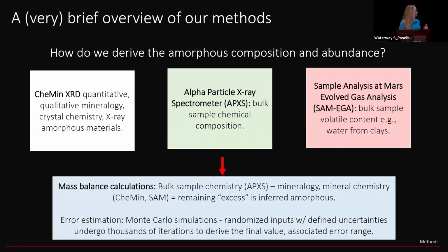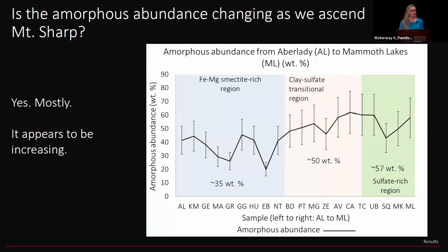And then this gets fed into a mass balance calculation, where we basically subtract the mineralogy and the mineral chemistry from the bulk sample composition. And again, this does not come without errors and assumptions, and I've been very clear about that with folks I've spoken to. The remaining excess from this is what is inferred as the amorphous component. So the first question I said I would address is: is the amorphous abundance changing? And the answer is yes, for the most part.